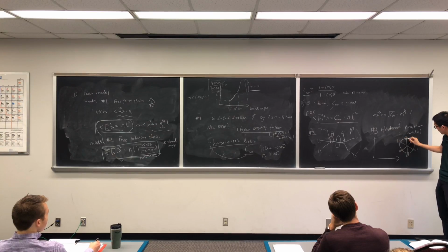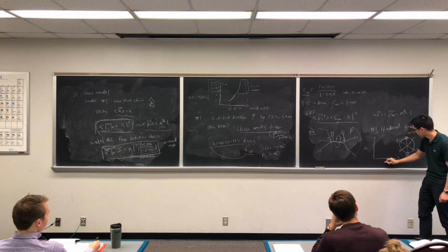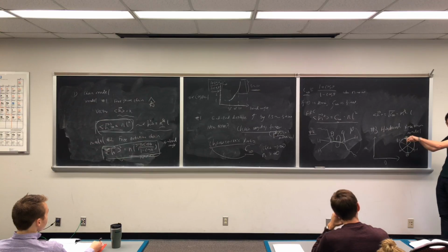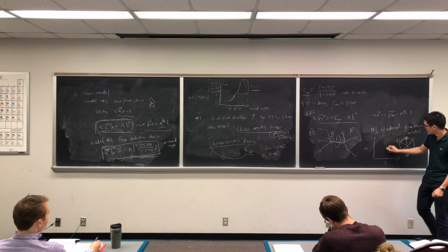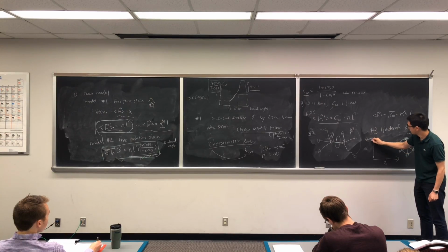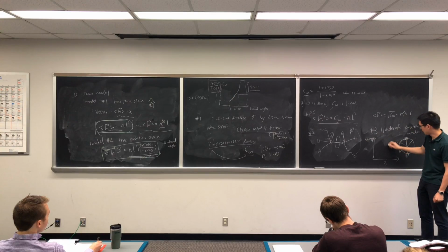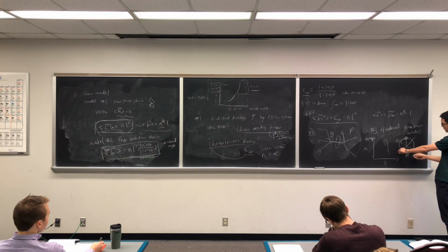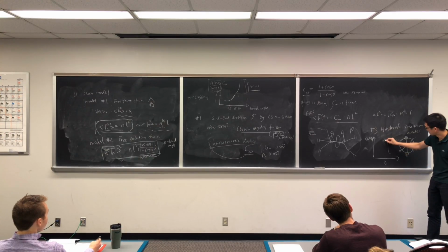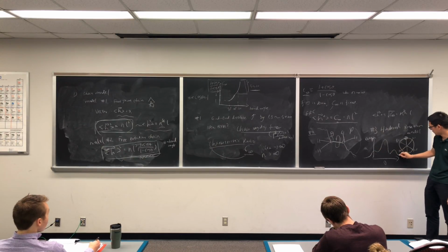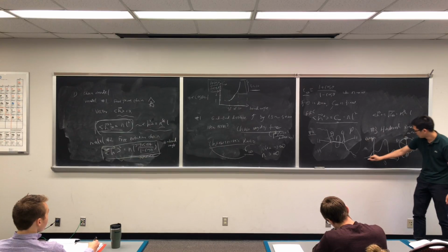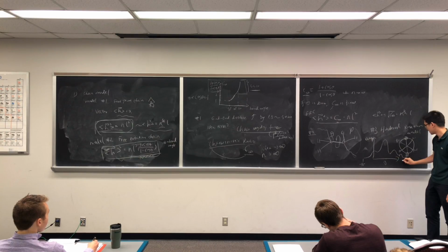As you see, if these are in phase with each other, or 0 degrees, this overlaps. If we rotate back, overlapping on top of each other, it will have the highest energy because of steric hindrance. So if we think about this energy term, you will have the highest energy, then you will have the lowest where it's sitting a little bit off angle. Then you have a minima, which is 180 degrees. Okay, so this minima is minus 180, this plus 180.